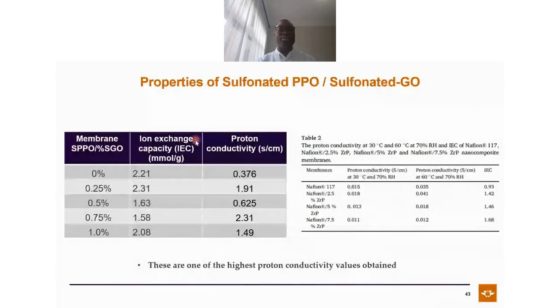What were the properties? Well, this membrane also had one of the interesting properties in terms of proton conductivity. These are the different types of membrane. You remember, initially there was a part where I presented the proton conductivity of Nafion. So look at the proton conductivity of the Nafion material compared to the conductivity of the material that you got. If you look at Nafion, it normally gets about 0.0 something in terms of conductivity. But when you look at this material, it had even a 2.31 conductivity. So basically, if you look at the ratio, it is very high compared to Nafion. So basically, this membrane can actually replace Nafion.